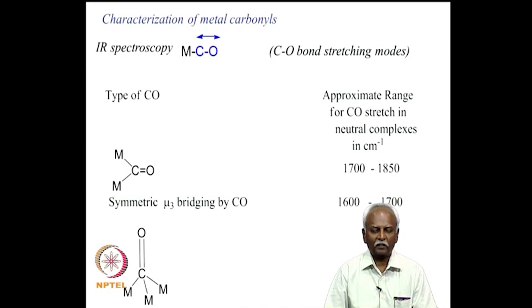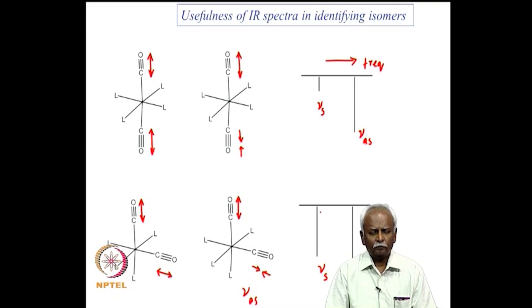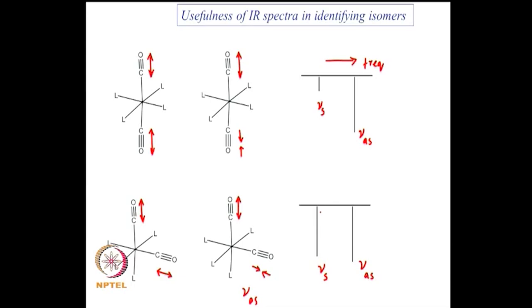If it is a terminal carbon monoxide, then the stretching frequency decreases significantly, and if it is a bridging carbon monoxide, then it is more like a ketonic carbon monoxide, and the carbon monoxide stretching frequency can be as low as 1600 centimeter minus 1 when it is triply bridging, as in the case of the compounds that we encountered, the iridium polynuclear systems, where we had triply bridging carbon monoxides. And in those cases, the carbon monoxide is in fact more like a ketone or a C double bond O or a C plus O minus species. So, you have very low carbon oxygen stretching frequencies. And it is very useful to use carbon monoxide to identify the type of compounds that they form.